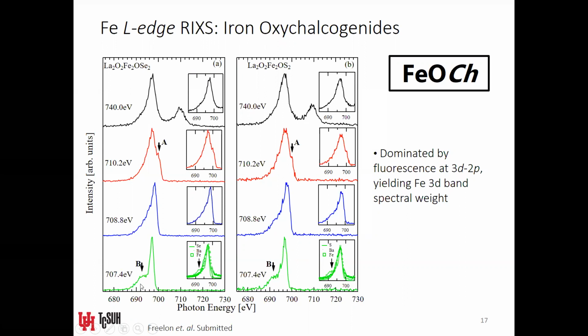And we can tune our incident X-ray energies to different values, and those different values are shown vertically up the page. And some of these values actually represent absorption edges. And what we can do is compare the resonant X-ray emission spectra that we get for our Mott insulator with that of iron-based superconductors. And so this figure actually shows that, but let me just talk about what you're seeing overall. This is resonant X-ray emission spectra that occurs as a result of tuning the incident X-rays to the iron L edge. And the occupied density of states spectra that you get are shown on the page.